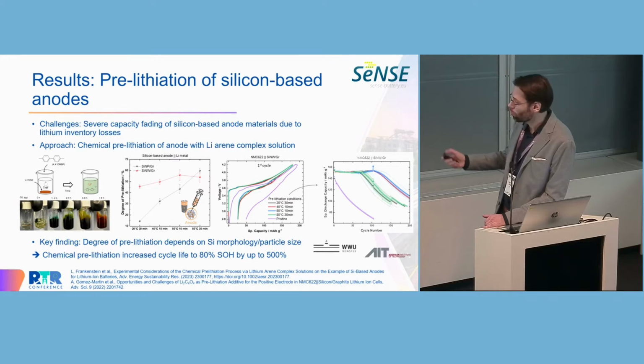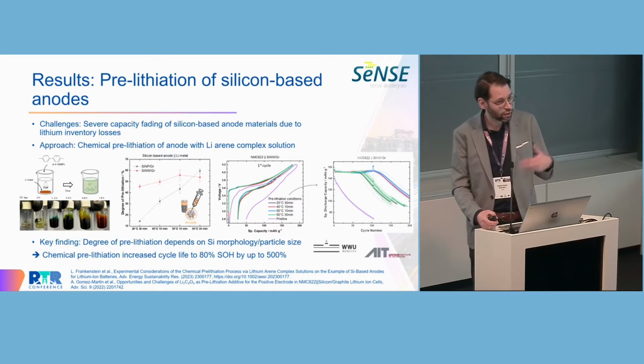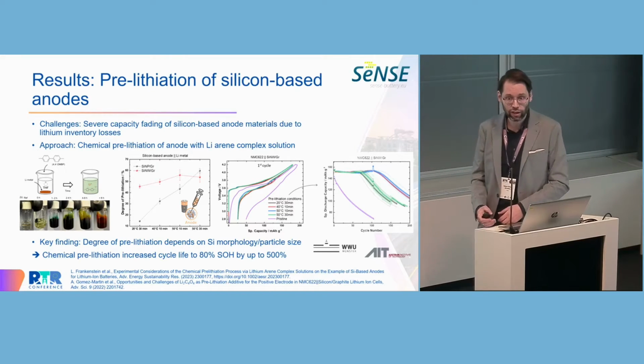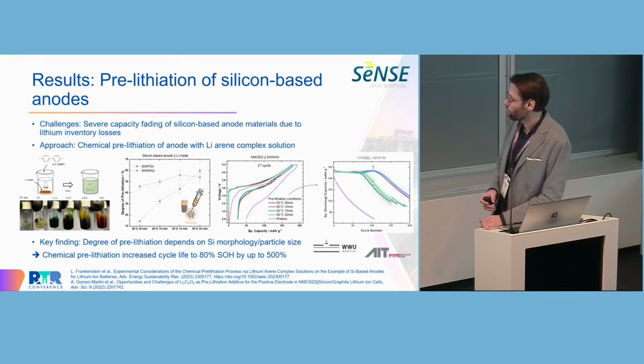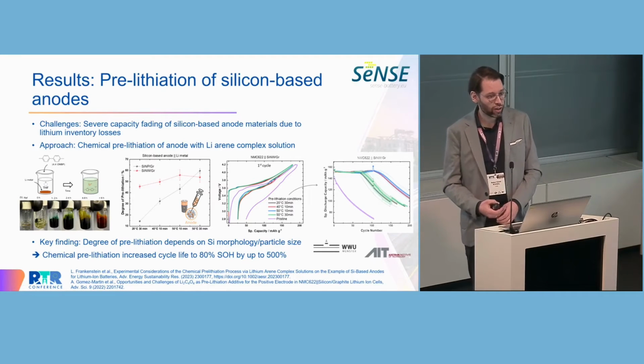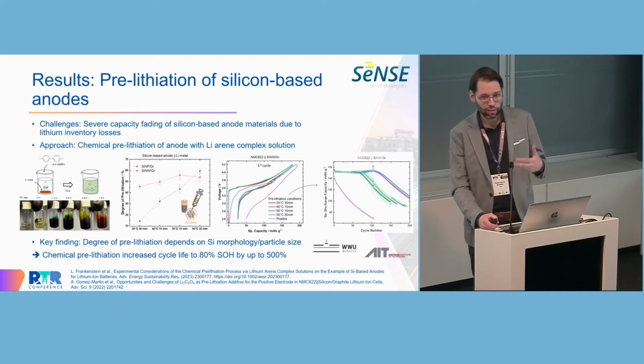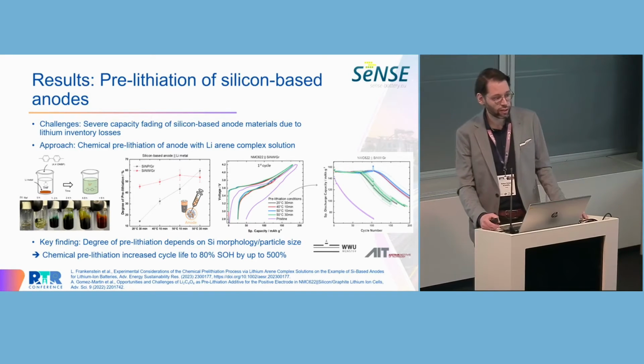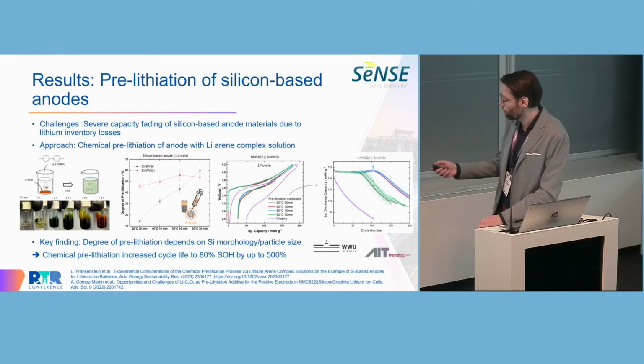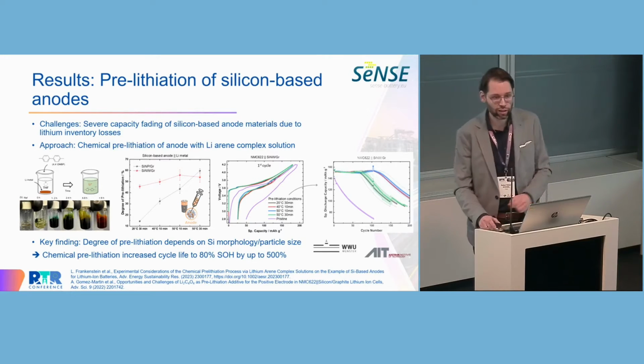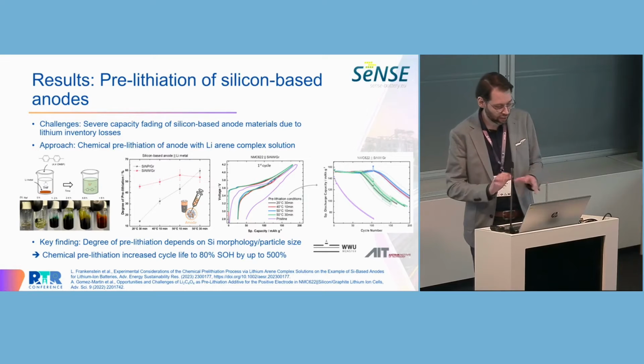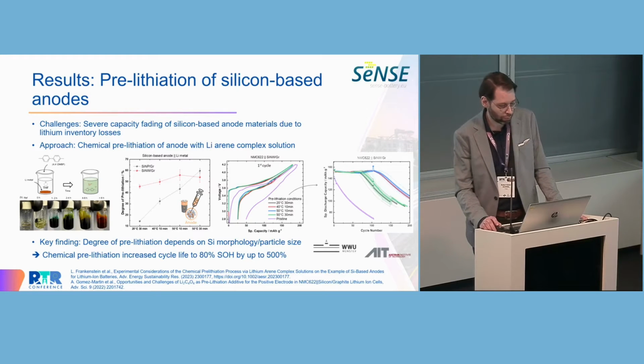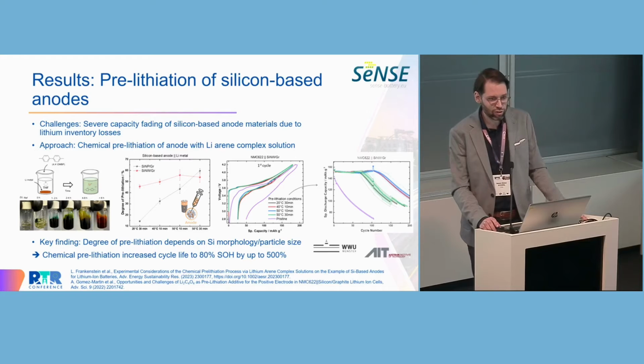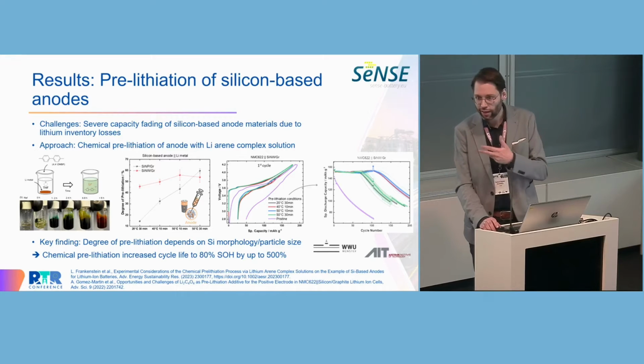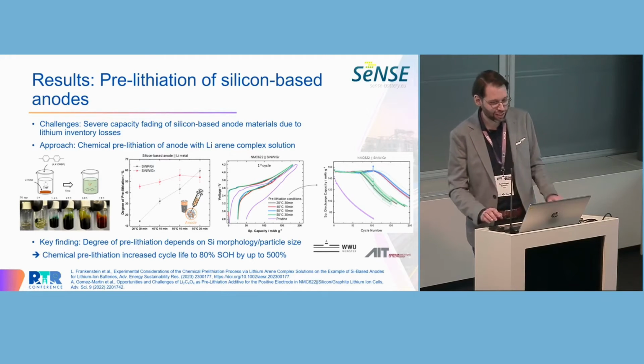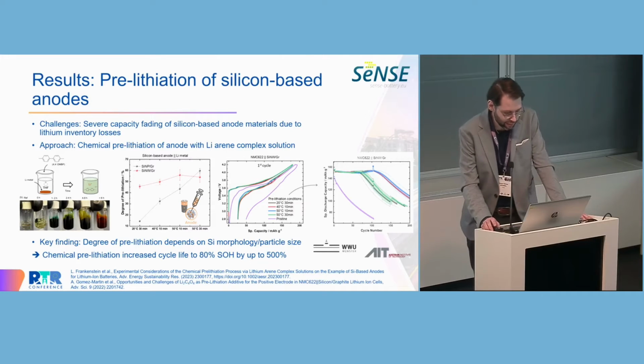Before then, probably the reservoir of lithium was depleted, and then we got into the fading regime again. But that was quite a nice result, and very recently, last month, we managed to upscale this technology and to also demonstrate it in small pouch cells, because these are coin cell results here. We now also managed to upscale it to 2 ampere hour pouch cells, which was quite a challenge because handling a lot of lithium metal, and in that case THF in a glove box, was not that easy, but in the end it worked